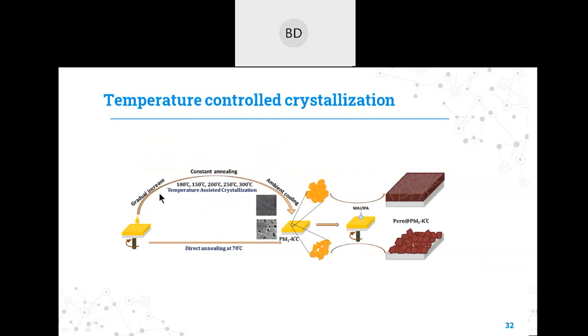We thought of changing some temperature profiling. We introduced some higher temperature annealing, where there is a gradual increase in the temperature, and for some time the temperature will be constant for a proper crystallization, and it will be cooled at ambient temperature so that the strain and stresses from the PbI2 film can be removed. So this gives a very compact, a very good morphology on the lead iodide film, which eventually can lead to